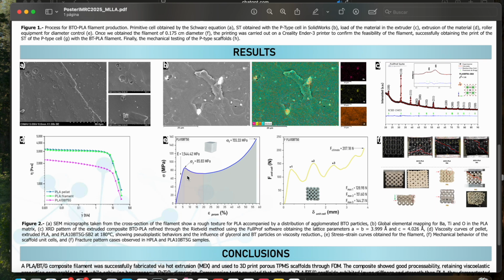The TPMS compression data reveal the key trade-off between stiffness and energy absorption. Compared with neat PLA scaffolds, PLA BTG lattices show lower initial modulus and peak stress, yet exhibit a broader stress plateau and higher absorbed energy before densification. The failure evolution shifts from brittle strut snapping in neat PLA to progressive, elastoplastic buckling and layer-by-layer collapse in the composite, which is the desired behavior for scaffolds that must carry load while avoiding sudden failure.